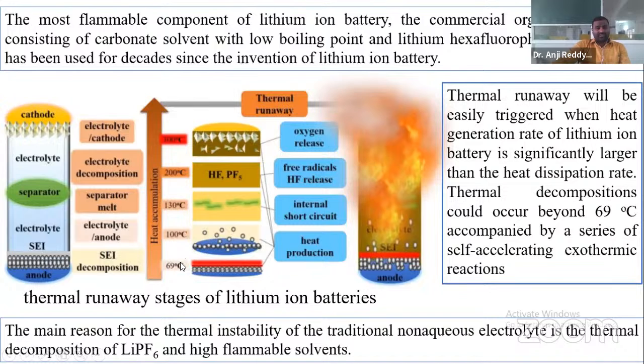First, from 60 to 100, main heat production is there. From 100 to 130, internal short circuit will happen. From 130 to 200, HF and PF5, these free radicals, HF will be released, and from 200 to 300, oxygen will be released. Then automatically the battery will catch fire. For that we need to extend the operational temperature range. This is the main phenomenon.